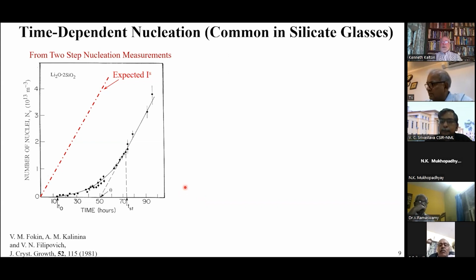One of the interesting things about silicate glasses is you can get very accurate measurements of the nucleation rate by doing what's called a two-step annealing treatment. And that is you take the glass, you anneal it, you heat it for some period of time at a temperature where the nucleation rate is very high and the growth rate's very low. And then you increase the temperature quickly to a temperature where the growth rate's very high, but the nucleation rate's very low. And what that allows you to do is to grow all of the nuclei that you produced on the first heat treatment. So you can do this very accurately.